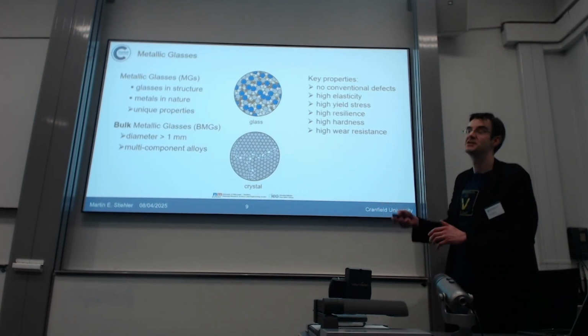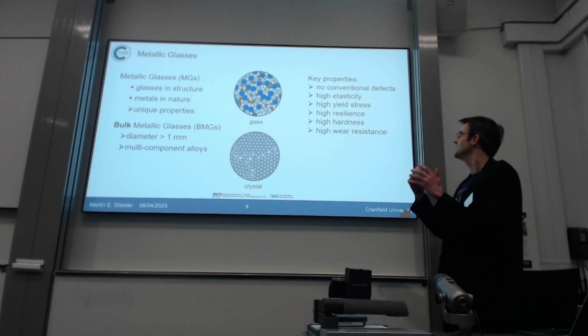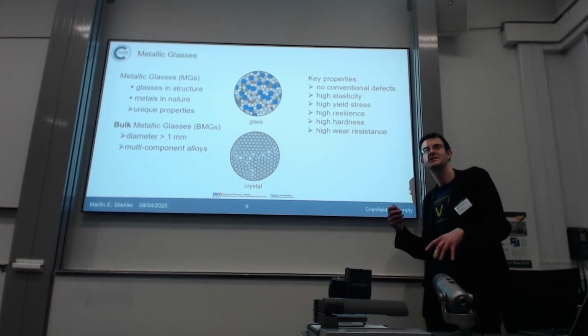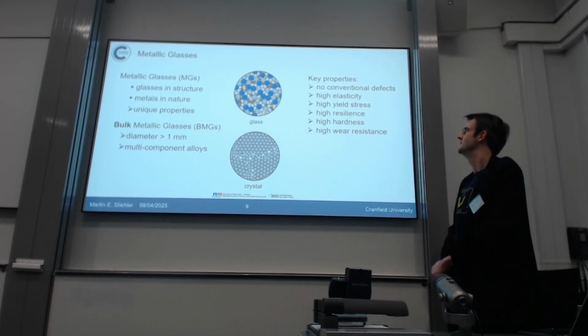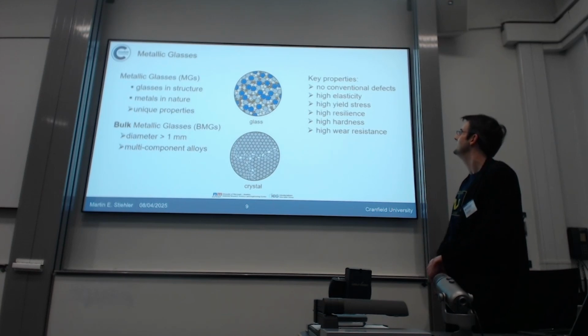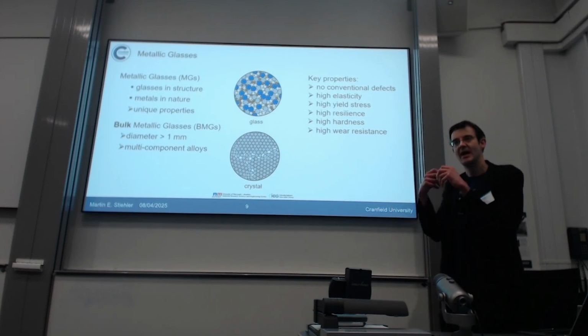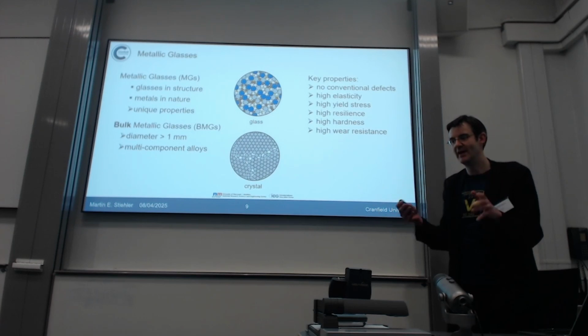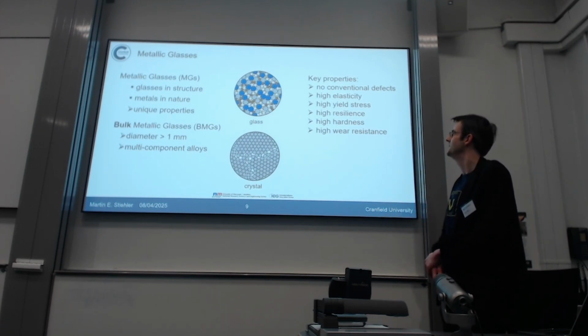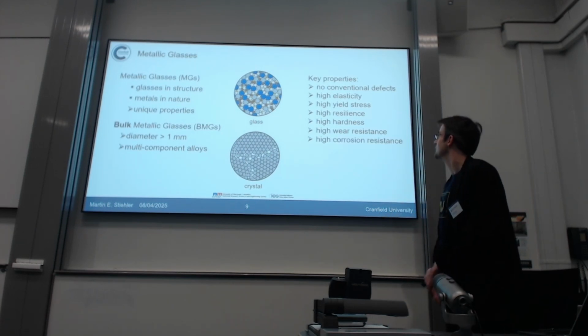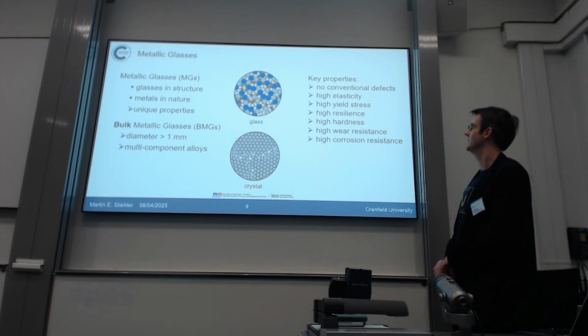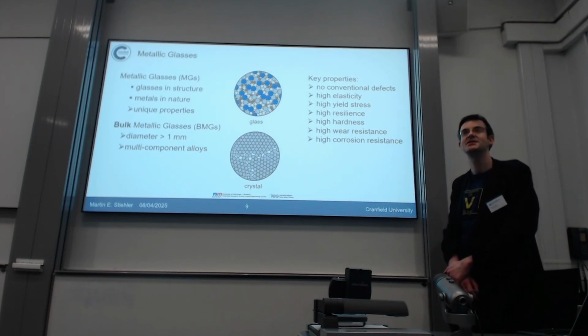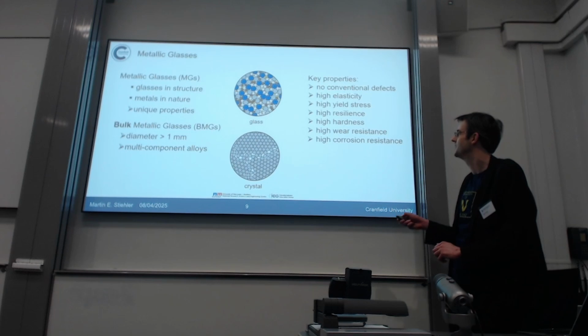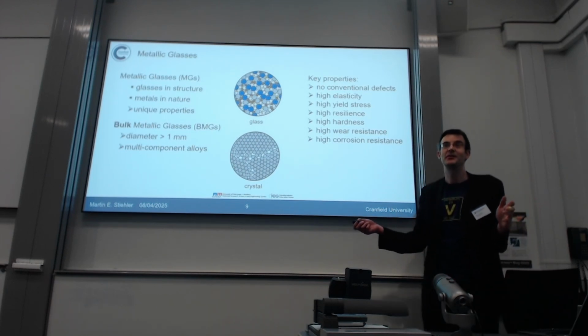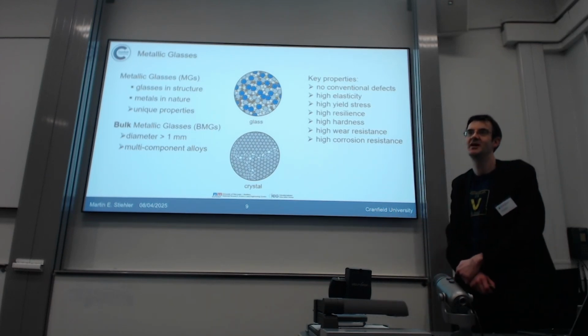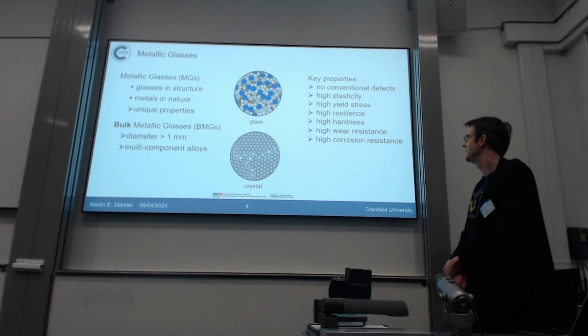In the metallic glass, as I said, everything is jammed. There are no slip planes, there are no defects, and so plastic deformation is not very easy to do, and also wear resistance and hardness would imply atoms to move somewhere, which is not easily possible in the jammed structure. There's also a high corrosion resistance because corrosion usually attacks at grain boundaries which extend to the surface of the material. If you don't have grains or grain boundaries, then corrosion has a hard time to attack these materials.